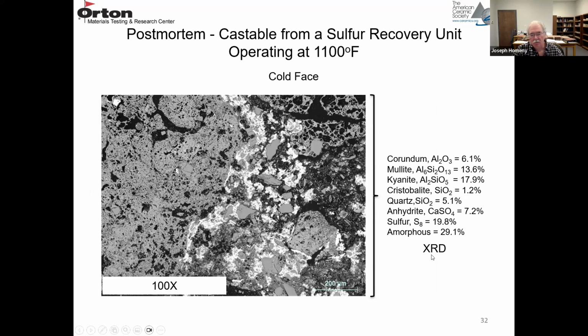We also did X-ray diffraction, XRD, on the cold phase. So there's some alumina in the form of corundum, about 6%. There's quite a bit of mullite, 13%. There's raw kyanite, that's Al2SiO5, about 18%. So the temperature was not high enough, 1100 degrees F. It wasn't high enough to transform the kyanite into mullite and cristobalite. There's a small amount of cristobalite, a small amount of quartz, probably in with the kyanite.